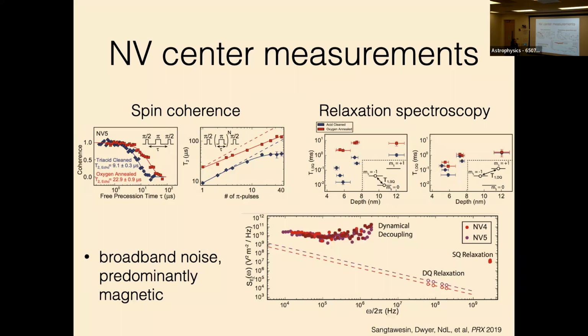And then if we do dynamical decoupling to try to extend the coherence, you can see that before this oxygen annealing, you actually stop winning from dynamical decoupling, so it saturates. And that's the real killer, actually, the fact that you have this really broadband noise that you can't even decouple away from. Whereas after this oxygen annealing, you still get scaling all the way out at 40 to 100 pulses.